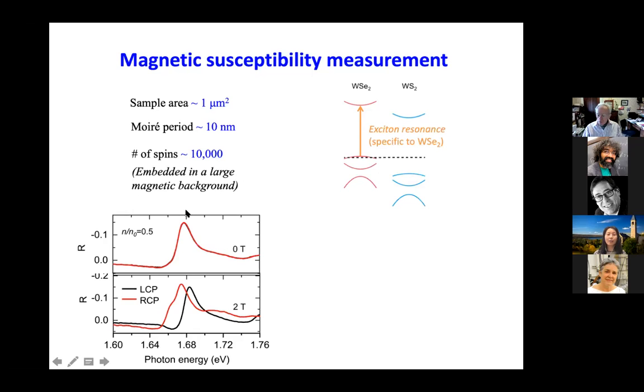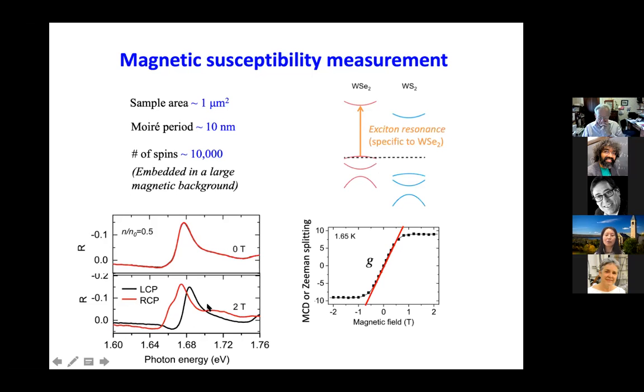So we look at the absorption difference between left circular polarized light and right circular polarized light. If you don't apply any magnetic field, those two valleys are degenerate, so there's no difference between left and right. But now if you apply an out-of-plane magnetic field, that magnetic field will generate a Zeeman effect. So one valley will be pushed up, the other one will be pushed down. And then you will see different absorption spectra for left and right. So now if you look at either the difference, how much the peak shifts, or just look at a fixed wavelength, how much the difference is, you get a curve like this. And this is linear when you apply a small magnetic field, and becomes saturated above 1 Tesla.